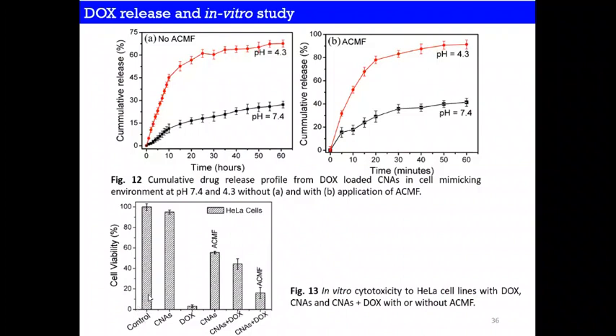So if you see the cell biology, this is the control, only the HeLa cells. When treated with the nanomaterials only, it shows around a 10 to 15% decrease. When only pure DOX is treated, then of course there are direct cell deaths. But when you apply the ACMF, meaning AC magnetic field, on only the nanomaterials, then there is around 40% cell death. But when DOX is used with the nanomaterials, the cell death is more than 50%. And when you apply the field with the hyperthermia and DOX, the cell death could be more than 90%.